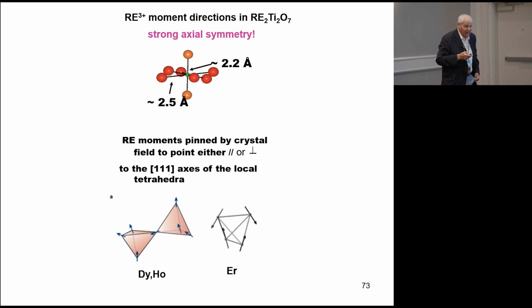And an implication of that is that the rare earth moments are strongly pinned along the directions of the 1-1-1 axes of the tetrahedron. And so, for example, here's a couple of the cases. These can be perfectly understood by examining the sign, as it turns out, of the axial term in the crystal field expansion. For dysprosium and holmium, we have the 2-in, 2-out model. The moments are parallel to the tetrahedral axes, and for erbium and ytterbium they are normal to the tetrahedral axes. So this is totally understandable in terms of the crystal fields.